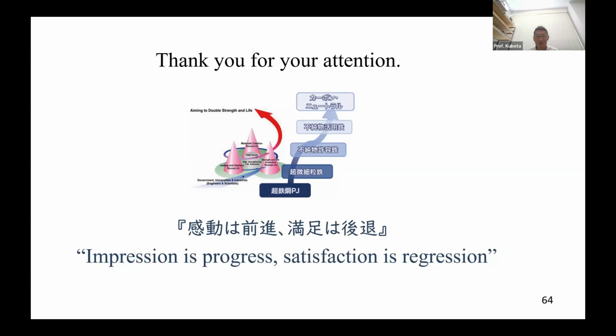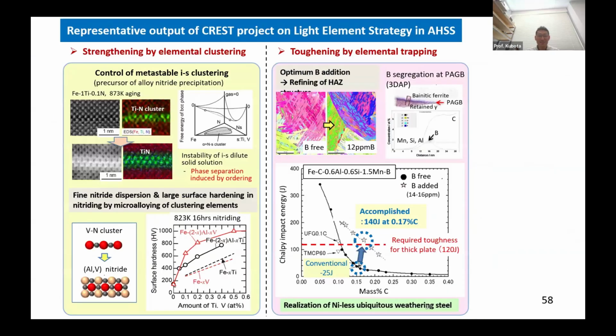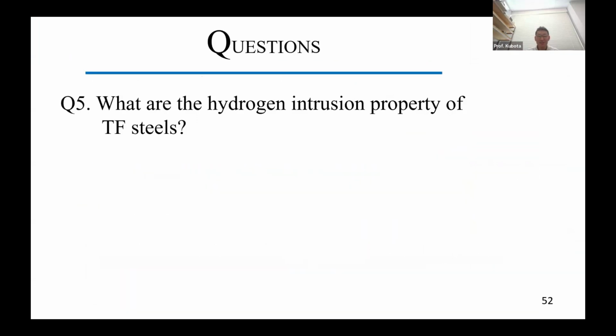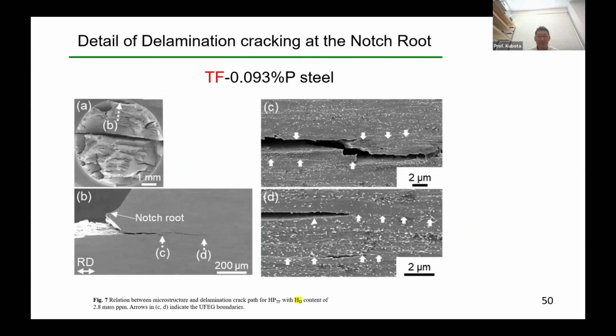Thank you very much, Tsuzaki sensei, for your very interesting talk on the P-doped steel. I have a question. In your experiment, the microstructure is controlled by thermomechanical treatment, but the loading condition is also controlled. Specifically, the loading direction is controlled to achieve good results. If the lamellar material receives a loading along the lamellar direction, what happens? I expect the toughness is significantly reduced. Am I correct? Yes, you are correct. Absolutely. This is the anisotropic microstructure.